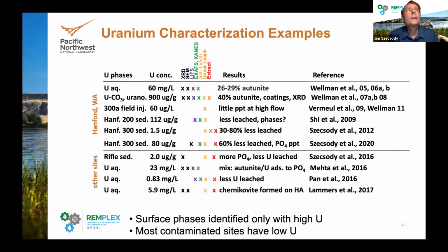To touch on that, I know there's a lot on this diagram, but what I'm trying to show here is different studies that have been done with uranium reaction with phosphates. If you have low concentrations of uranium in the sediment, pretty much all you can do are either extractions or leach experiments. If you want to identify what phases are formed, you actually need much higher uranium concentrations. So you either need to add uranium, as was done in this first study, and then you can figure out what phases are formed, or you need to work with field contaminated sediments that have pretty high uranium concentrations.